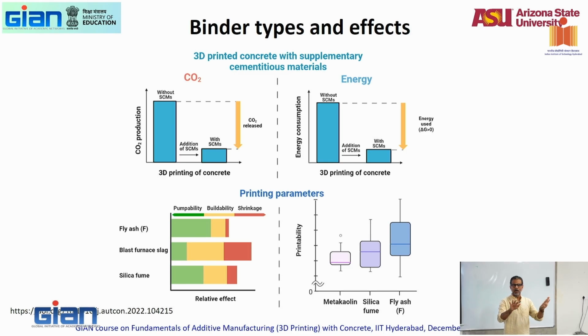Assuming that particle sizes are in the general range of cement, they're not extremely fine, not extremely coarse. Why fly ash? What will the shape do? Spherical shape, what will it do? Let's talk in terms of what we have been hearing yesterday and today. So what is yield stress? It is a stress that is required to be overcome to initiate the flow. What will fly ash do? What will a spherical particle do to initiate flow? It will reduce the friction between particles. The smoother particles, the ball bearing effect will start to make it flow, roll better. The resistance to flow is lowered. Fly ash will do a good job.